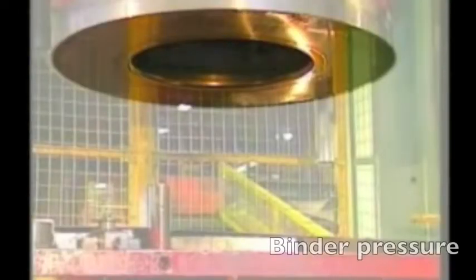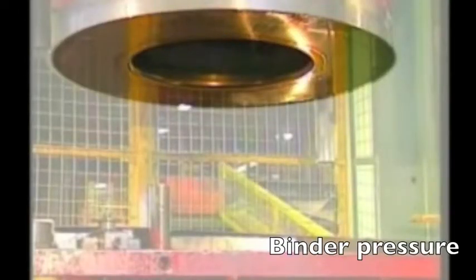The binder pressure, which dictates how a material blank is held in place, needs to be set for each material. For example, carbon steel has a binder pressure of 600 pounds per lineal inch, and stainless steel has pressures of about 1800 pounds per lineal inch.